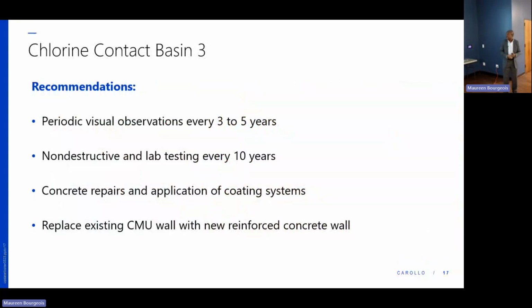we are recommending concrete repairs and the application of a coating system to protect the structure and extend its longevity. And we are recommending all these repairs and coating applications to take place within the next 3 to 5 years. So it's a good time to actually do it. And that'll also be the same recommendation for replacing the CMU wall, the concrete masonry wall. We are recommending replacing that with a concrete wall, since that will give you more durability. And that can also happen during the repair work within the next 3 to 5 years.